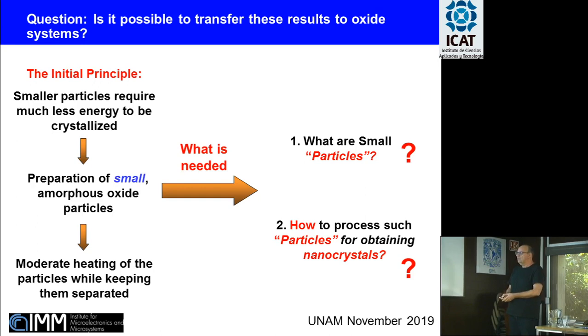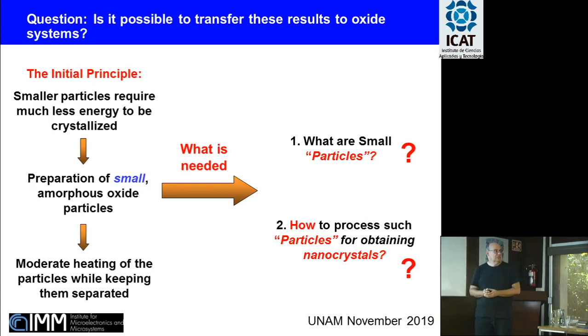Then if we prepare small amorphous oxide particles, no more cadmium selenide, and we slightly heat them while keeping them separated in order to limit the growth, can we prepare oxide nanocrystals by using this general principle? This is very easy to say, no? To develop this initial principle, to have some different idea from cadmium selenide.